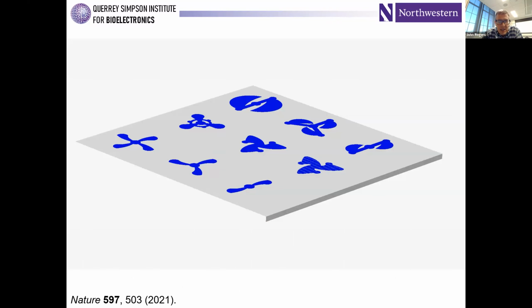And we've been working on different kinds of approaches to affect a 2D to 3D transformation process, originally of planar device structures. And we were able to put together some strategies that rely on mechanical buckling. And this is a finite element modeling rendering of that kind of 2D to 3D transformation process. And it really starts with a biaxially strained elastomer substrate with planar precursors bonded at specific locations to that elastomer, such that when the pre-strain is relaxed, it applies compressive forces to those structures, thereby inducing a kind of buckling process that geometrically transforms those 2D structures into well-engineered 3D systems, in this case, microchips on the planar surface of that elastomer with wings that move up out of the plane to create this kind of helicopter-like flight dynamics in free fall.